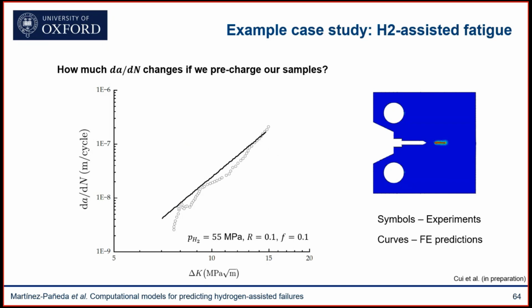But then we said, okay, let's use the model to try to understand things that we cannot figure out from the experiments. One thing is that these experiments are done as soon as possible, basically. So you don't pre-charge your samples. You have to pre-charge them for 24 hours because that's the time that it takes to get the machine set up and running. But then after that, you just load your sample.